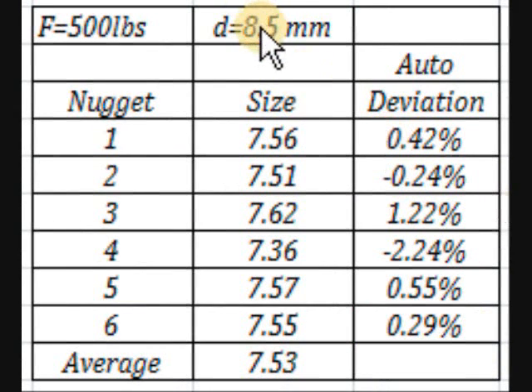This time we change the diameter of the cap. We have physically changed the cap to an 8.5 millimeter cap, and we make 6 welds. We expect the nugget size to be about 1 millimeter less than 8.5, so about 7.5. The average of the 6 welds resulted in about 7.53, which is extremely close. This time the largest deviation is only minus 2.24%.